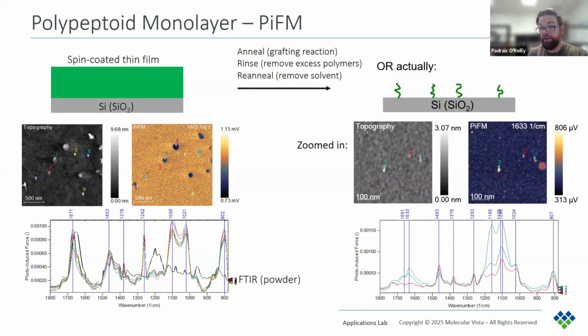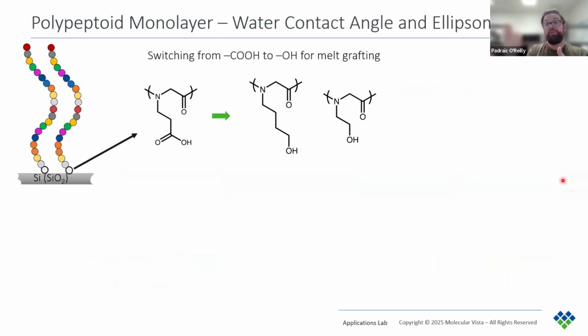Now the green and blue spectra are taken on some of these brighter regions, and we see that there is this carbonyl peak. So this shows that while water contact angle measurements suggest that there was a peptoid monolayer, PiFM shows that there are only small submonolayer fragments. Then they revisited the composition of the molecules and they changed this binding group from a carboxylic acid to an OH group.